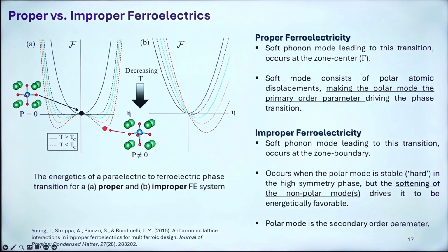Yeah, so then what are proper and improper ferroelectrics? When we discuss this, these two are the things. Now we are going to connect it with the soft modes, which I mentioned in the beginning. How to understand this? By looking into the phonon dispersion relation. In proper ferroelectricity, the soft phonon mode leading to this particular transition occurs at the gamma point, which is the center of the Brillouin zone, and the soft mode consists of a polar atomic displacement, making the polar mode the primary order parameter driving this transformation.